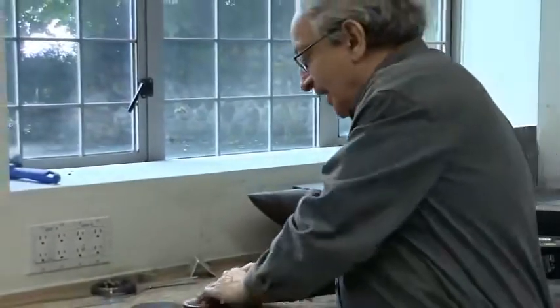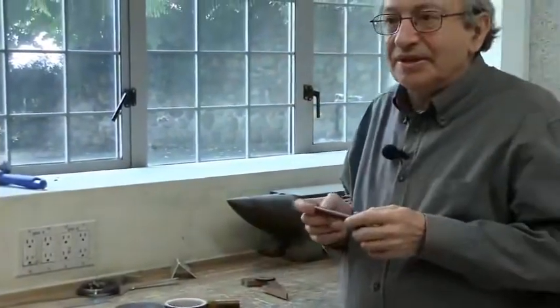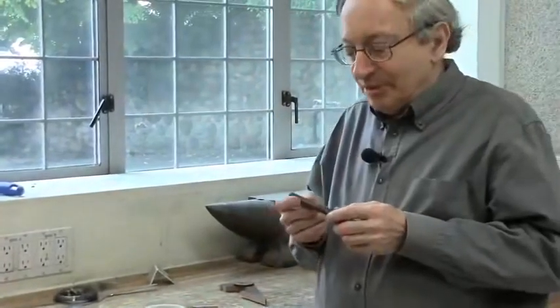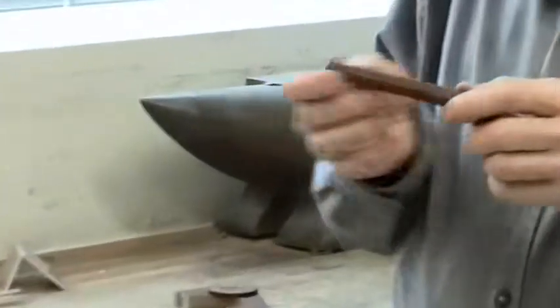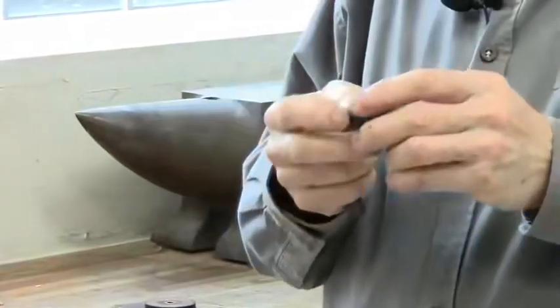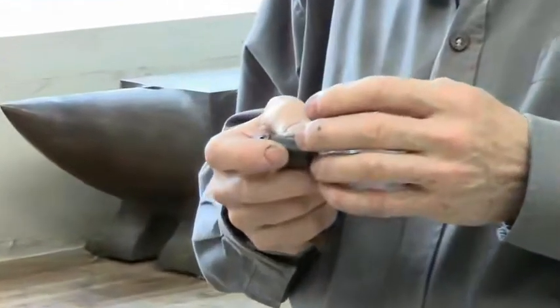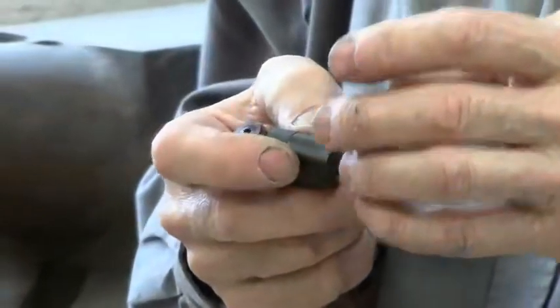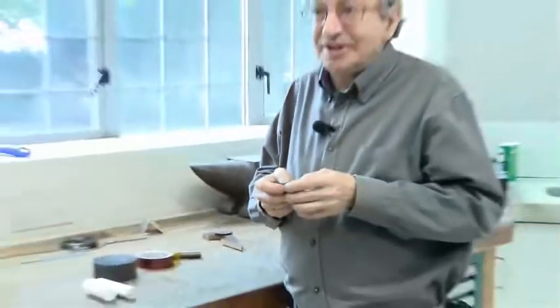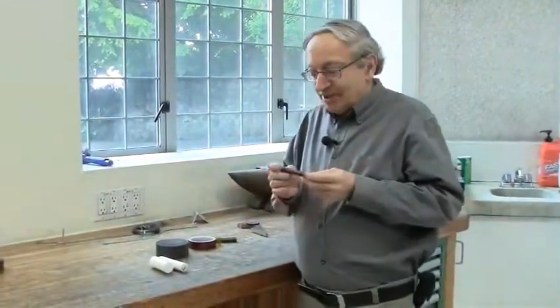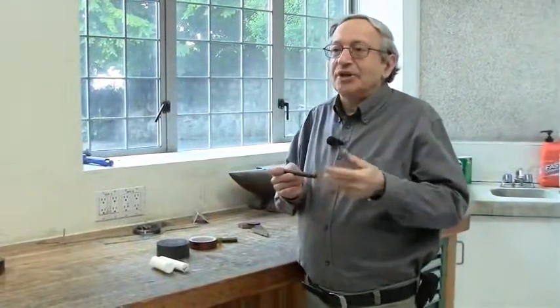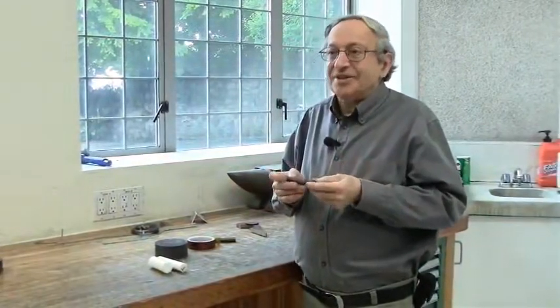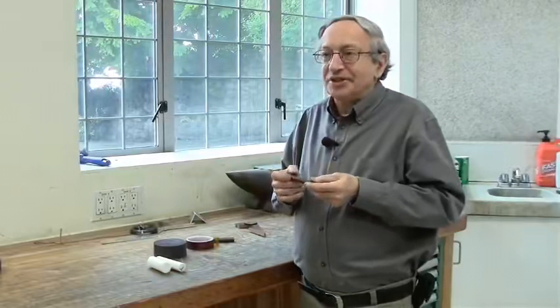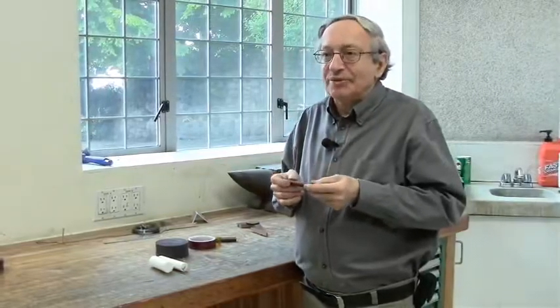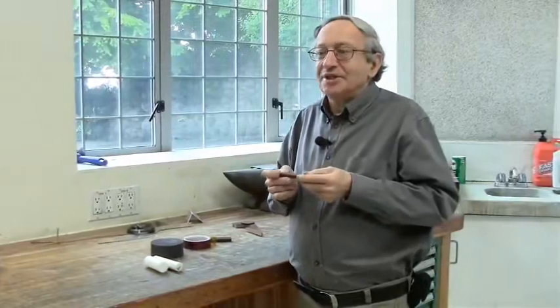Okay, and it's available as bulk material under the trade name Vespel, made by DuPont, either virgin and then brown shape, or filled either with carbon or filled with moly, MoS2, or filled with different materials to make it a better bearing material. So this is an amazing material. It can regularly work at 300 C. Okay, it holds threads very well, it's very rigid, it doesn't distort, it holds shapes very well. It has only one catch: it's terribly expensive.